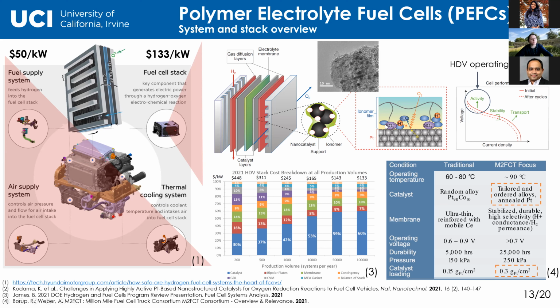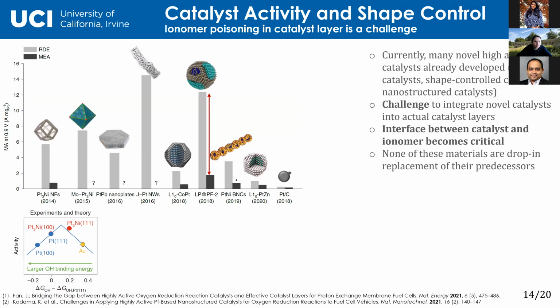So what's been done historically? Now we're just going to transition to reviewing what's been done in the literature. If you look into the materials research community, they've done an amazing job developing new catalysts. So you have the platinum alloy catalysts that are nanoframes, octahedrals, you have thin films, you have some ordered intermetallics, you have all kinds of other catalysts, and this is their mass activity. That's how they evaluated how active they are. And the gray shows simple setups such as rotating disk electrodes. So this is a simple pre-screening electrochemical tool you can use to evaluate your catalyst, or you can put them into a membrane electrode assembly and test them in the fuel cell.